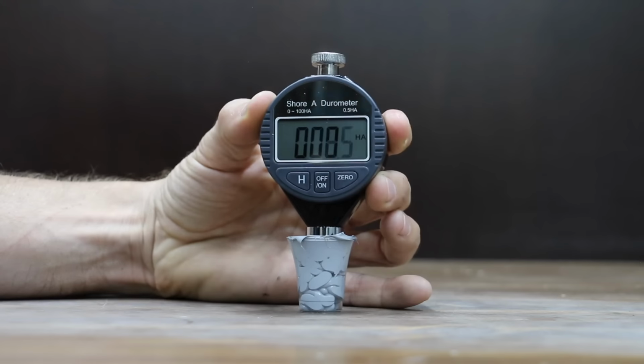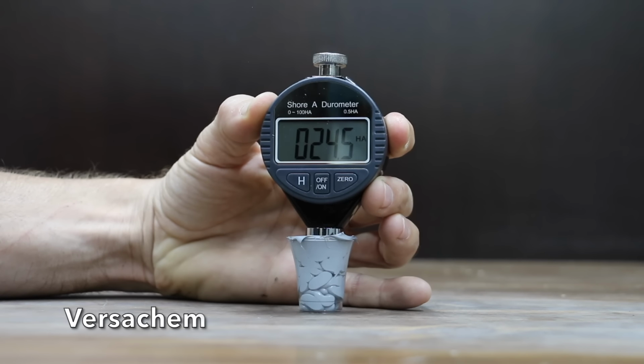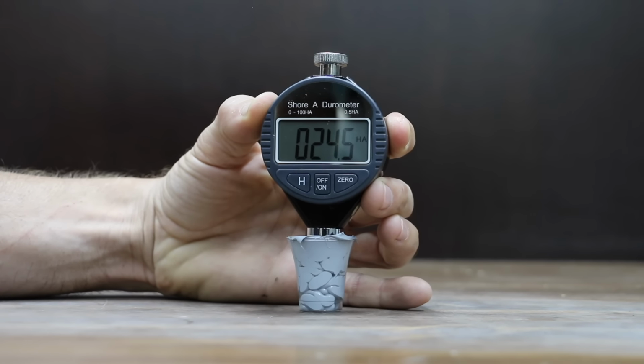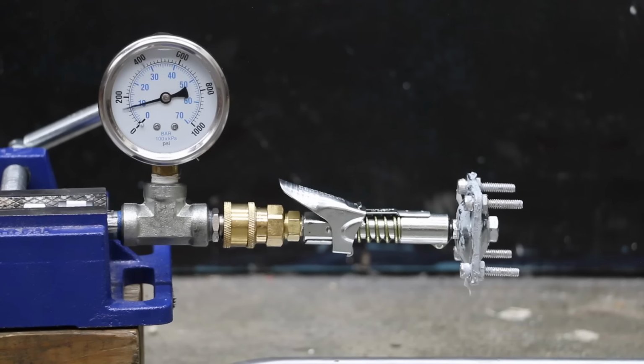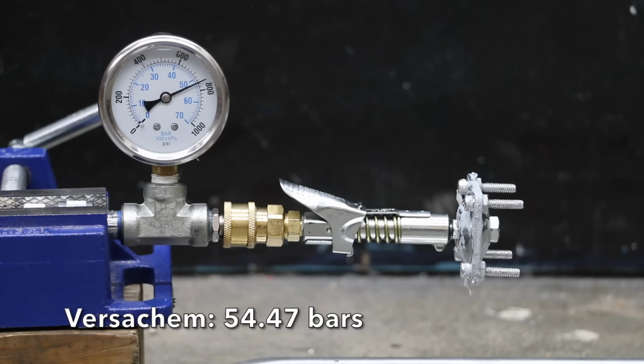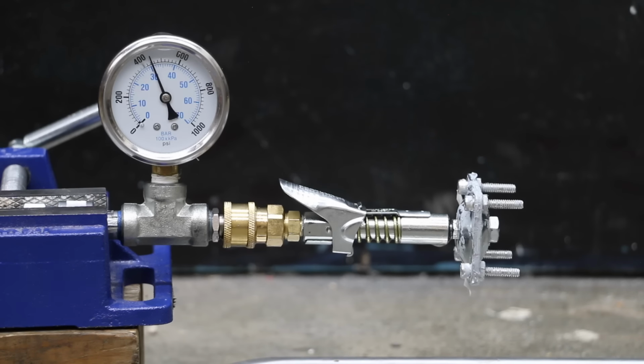Very impressive. And the Versachem is a gray RTV with a hardness of 24 and a tensile strength of 67.8. So not as hard as the Permatex, but harder than the JB Weld. And the Versachem did a great job at 790 psi, which is good enough to move into second place behind the JB Weld.